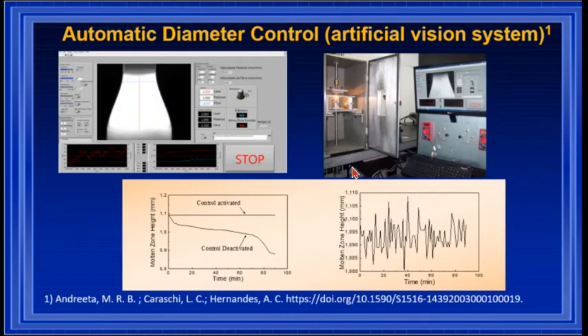To avoid diameter fluctuation, we developed in our lab an automatic diameter control based on an artificial vision system. The system looks at the molten zone and then controls the laser power and the pulling speed to control the diameter.